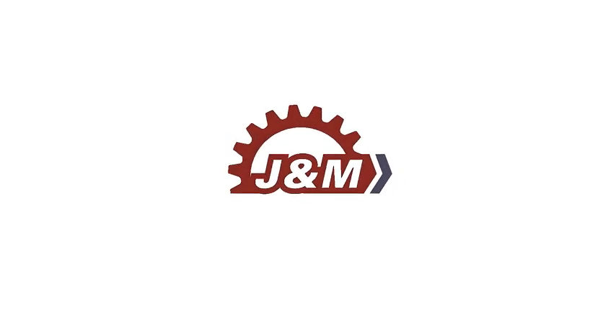So for example, a standard part needing maybe plus or minus 0.01 millimeter, that might take 2 passes total, the rough plus 1 skim. Roughly doubles the machining time compared to just roughing. Okay, makes sense. But if you need a high precision punch, maybe aiming for 0.005 millimeter tolerance and that nice 0.2 to 0.4 Ra finish, you're probably looking at 3, maybe 4 passes. And yeah, that might take, say, 3.5 times longer than the rough cut alone. More passes, more time, tighter tolerance.